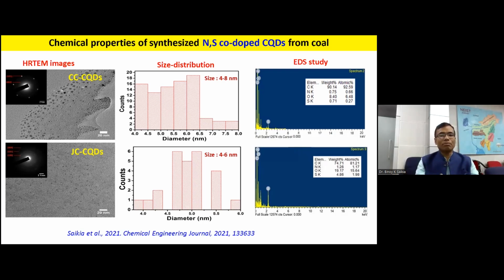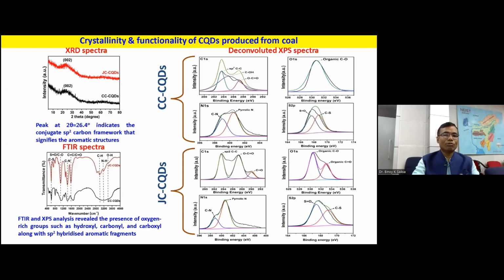So our coal-derived quantum dot has also the in situ co-doping of nitrogen and sulfur, which is required by many researchers in their application field. So this also we have tried, and we got a very interesting sulfur and nitrogen quantum dot, and we found that those nitrogen and sulfur are basically organically bound, which makes it also interesting to give the requisite emission in the visible region. In the XPS we found that the sulfur is related to the carbon and also to the oxygen, and the nitrogens are pyrrolic and amine nitrogens. So this is also an interesting property, which makes it a very efficient color-emitting quantum dot.